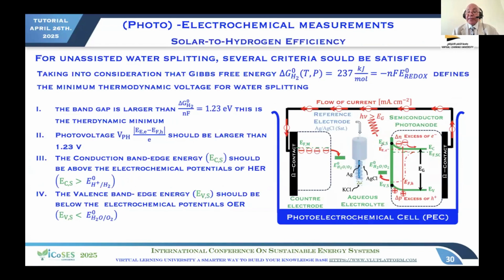Yes, so you see, I just show here a platinum counter electrode, and that's the level of the work function of the metal of the counter electrode. And I show you here the N-type semiconductor. And you see the two levels here, the level of hydrogen evolution and the level of oxygen evolution. Here there is a mistake. That is H+/H2, not the other.